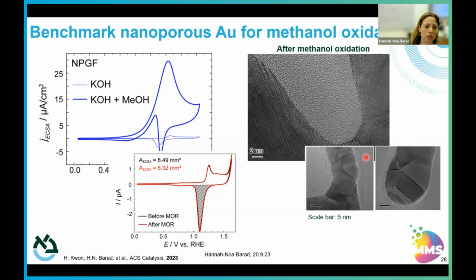What's really nice about this is that pretty much this can be used as a reference benchmark material for anyone who wants to try and look, for example, in the case of gold, how the different additions of impurities affect the gold activity. So you don't only have to look at silver anymore. You can try putting in copper, you can try putting in iron, you can try putting in nickel, and seeing the different amount of dopant levels or impurity levels, how they affect the activity. So our material is really, really pure and really clean, and that's why it's a significant benchmark reference material.